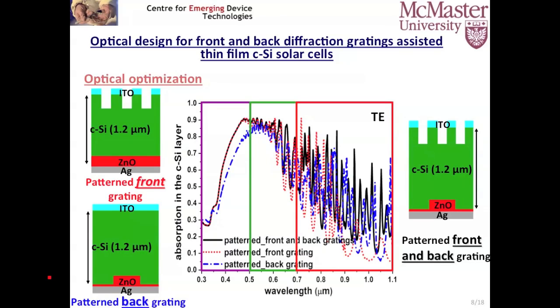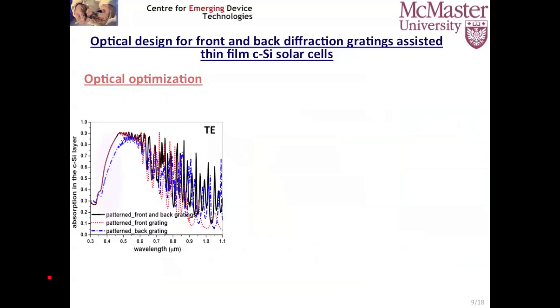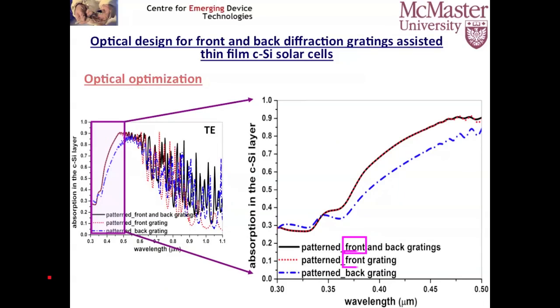When we look at the absorption spectra, we can divide it into three main regions. In the short wavelength range, there are no obvious absorption peaks because the incident light can be absorbed by the silicon directly. In the middle wavelength range, there are several regular absorption peaks. And in the longer wavelength range, there are multiple irregular absorption peaks, though they are hard to see directly.